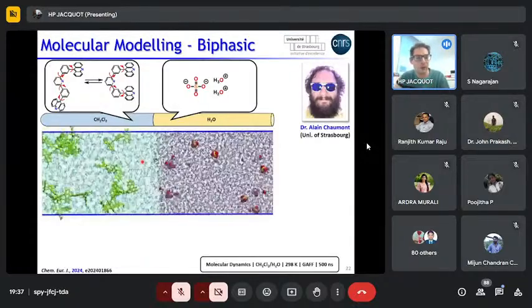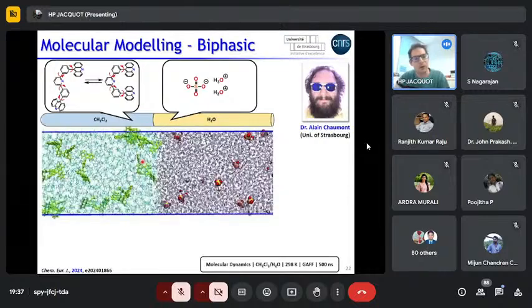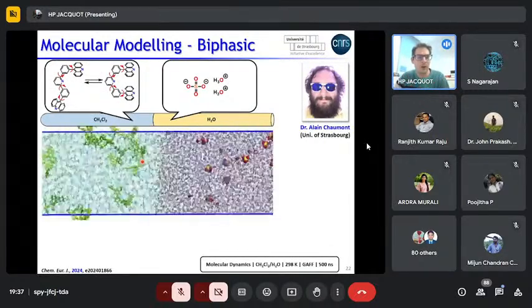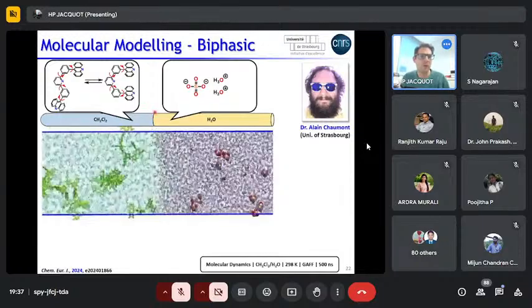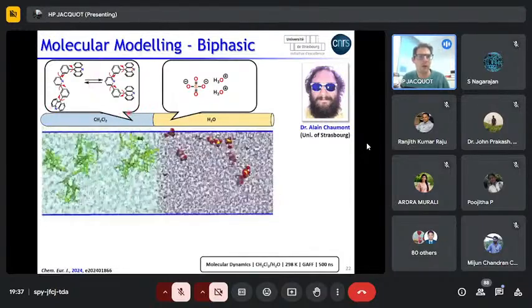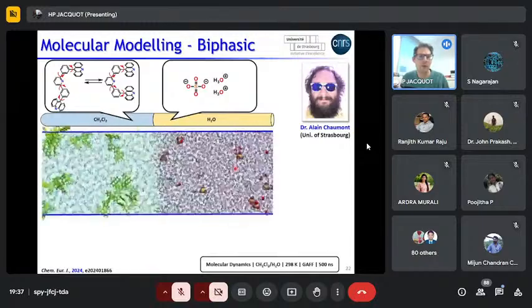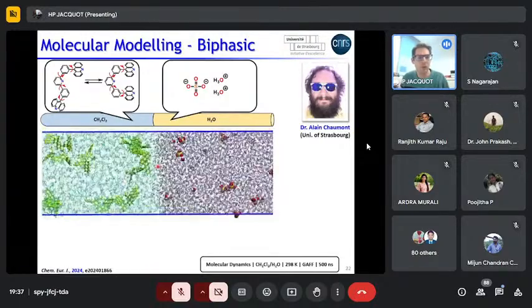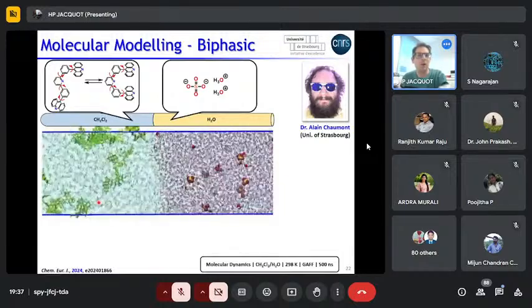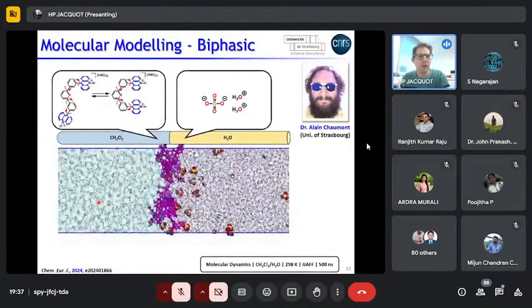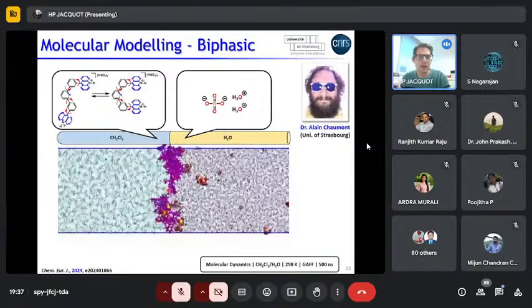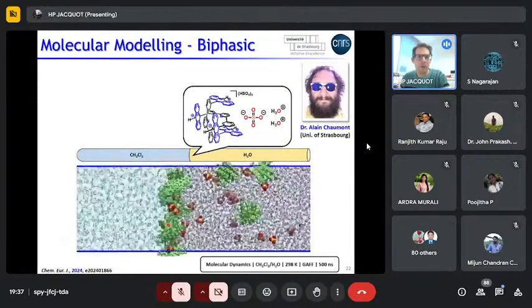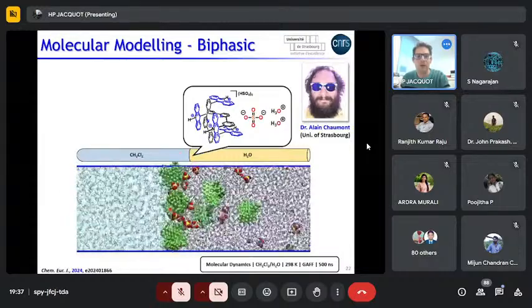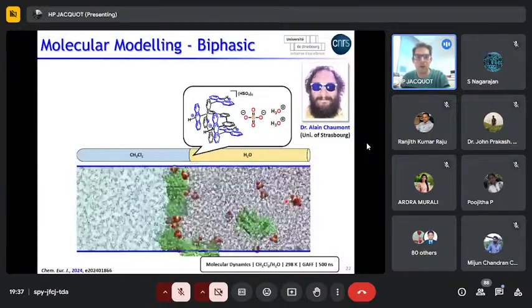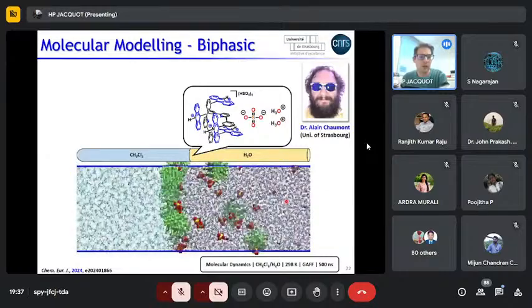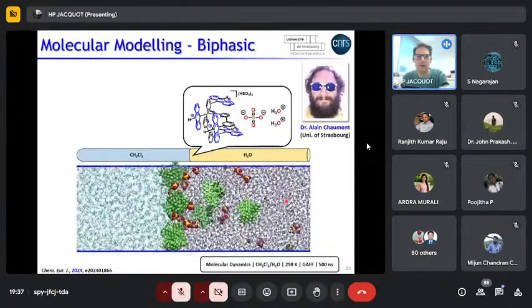So Alain Chaumont, who did these calculations, started from three case scenarios. The first one was the initial state with the non-protonated tweezer in DCM and then some sulfuric acid in water. And you see that mainly the tweezer remains in DCM. Then when you start from the protonated molecule, it stays mainly at the interface. And finally, when you start from the dimer, this dimer also mainly remains at the interface, but still you have some in water. So basically, these calculations confirm that everything occurs at the interface.